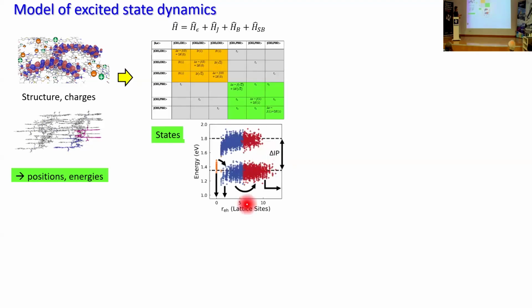We build this model considering that we have some structure in which we coarse grain our molecular structure into a lattice or an assembly of points. Then we set up a tight binding Hamiltonian where we allow the sites to interact with each other. So an exciton on a single molecule can interact with excited states localized on other molecules, both forming neutral excited states and charge transfer excited states. So we have a two-particle Hamiltonian in an electron hole basis. That means that we have both excitons and charge transfer states in the same model.